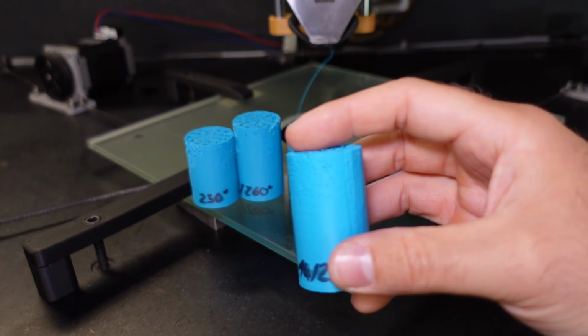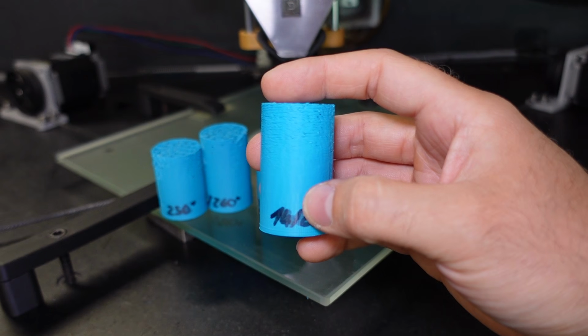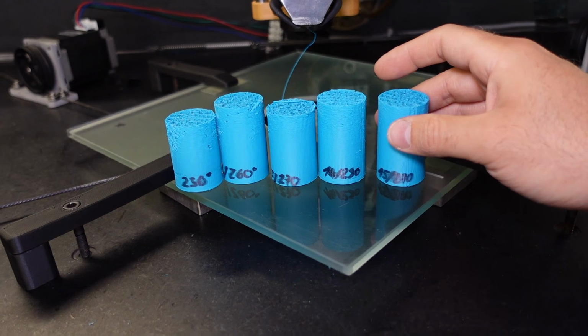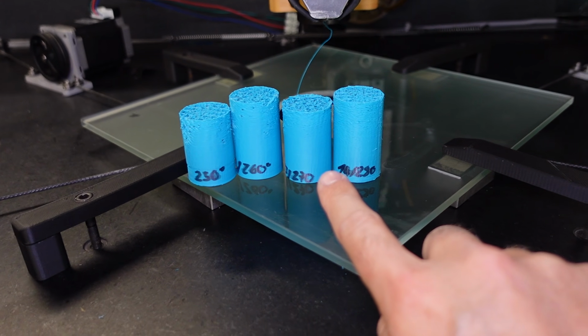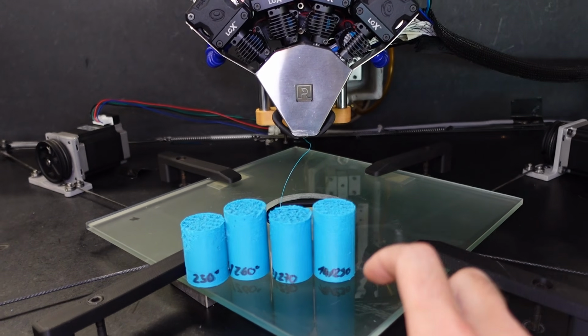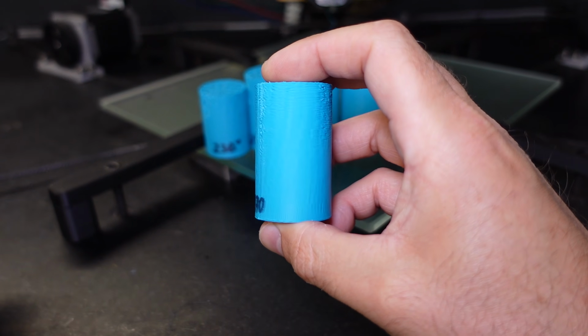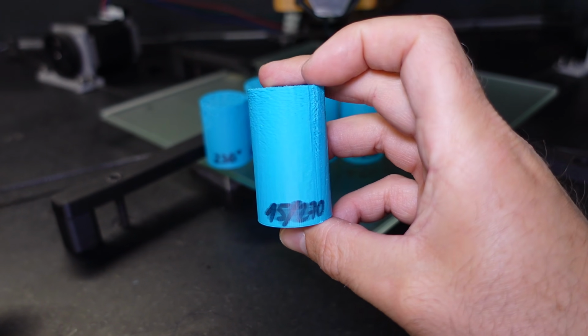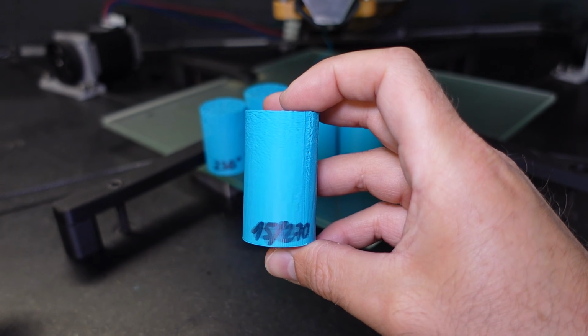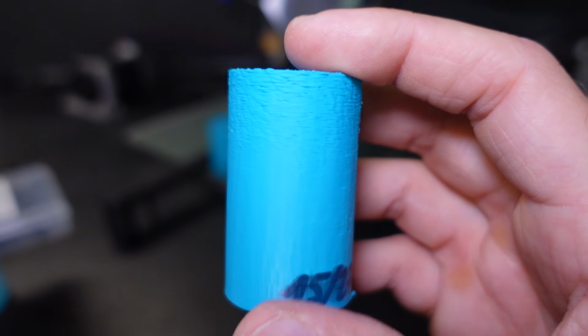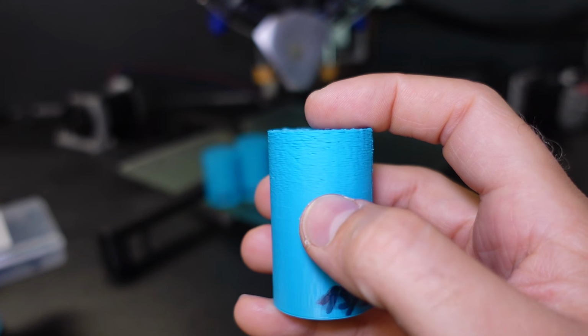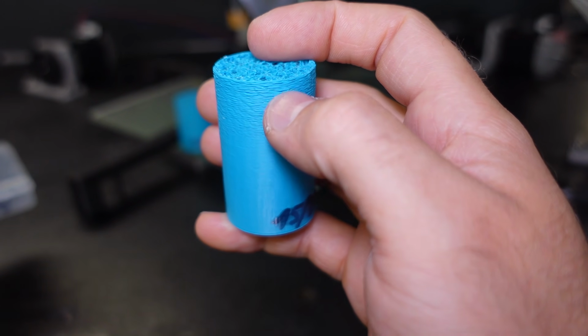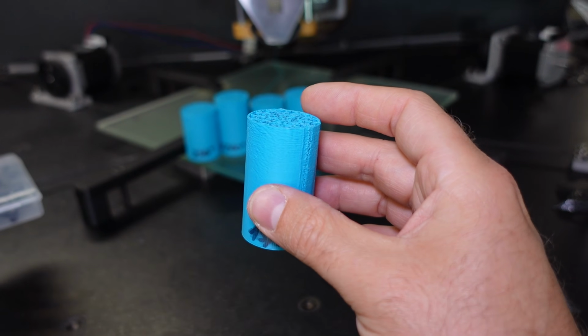280 then again started to look a bit worse. So with the last one I dialed it back to 270. And all of these are done at half a bar of cooling pressure on the duct. This one is at 1 bar of cooling pressure. This is going all the way up to 1500 millimeters a second and doesn't look too bad. Here, starting from let's say 1100 or something like that, it starts to get a bit wobbly, but this may also be because it's wobbling or rocking on the plate.